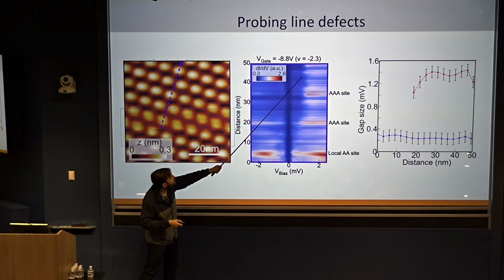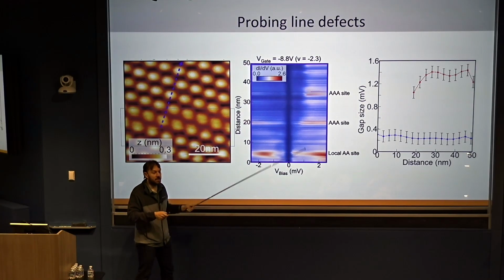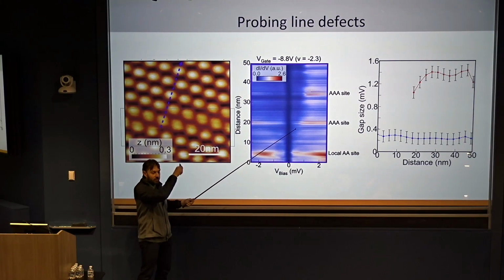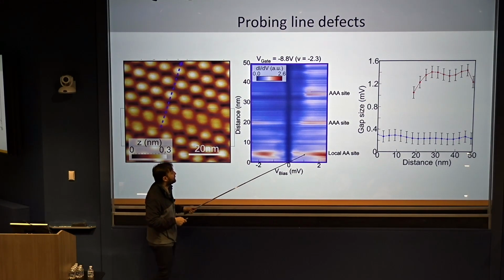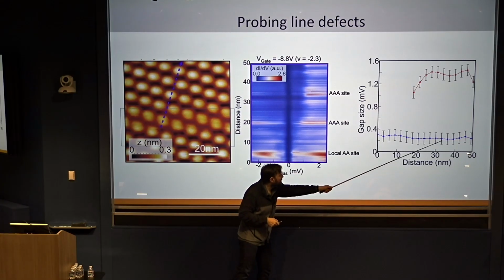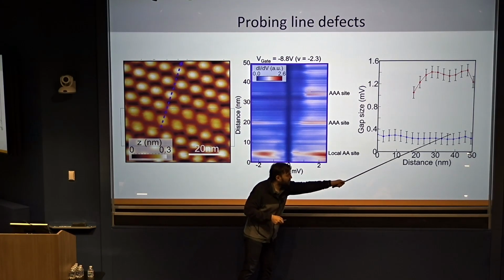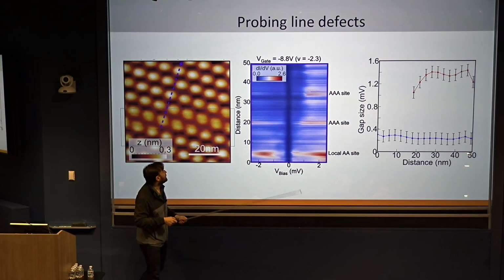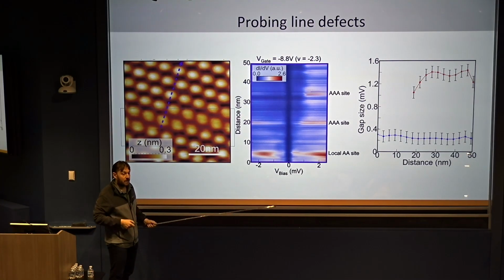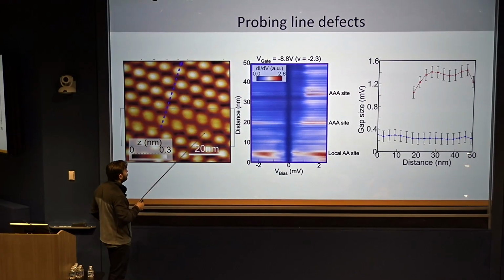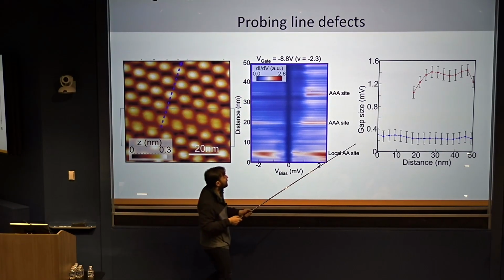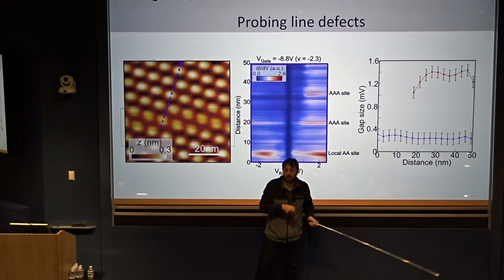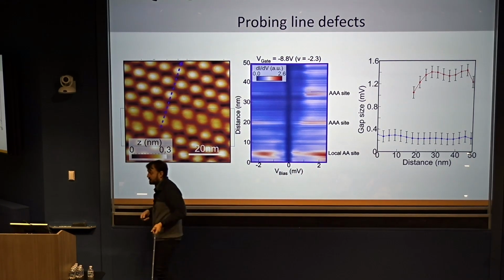These very sharp lines are actually atomic resolution images, because you're going across the atoms in some random directions. But wherever you can extract it, you can see that the value of the smaller gap is roughly constant. So the smaller gap doesn't care if you are deep in the homogeneous region or close to the defect, while the larger gap does care and disappears near the defects.